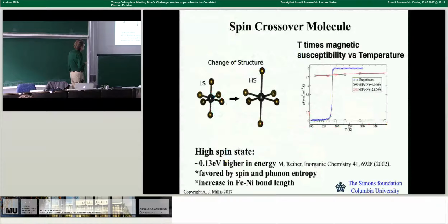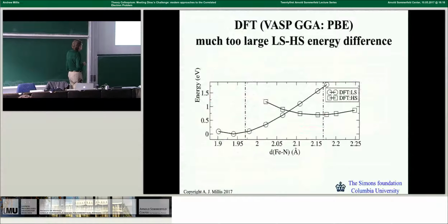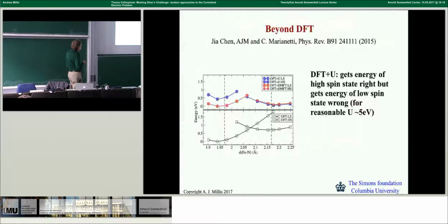So this is what I showed you before. You have this spin crossover molecule. All right? This is the density functional theory I showed you before. If you do DFT plus DMFT, well, if you do DFT plus U, which is the Hartree approximation to this theory, in fact, you go from having the energy 0.6 eV, which is way too big this way, to having the energy almost 0.6 eV big in the wrong direction. You include the quantum many-body theory, and now the two states have approximately the same energy. All right? So this combination of band theory and many-body theory is doing something useful for you.